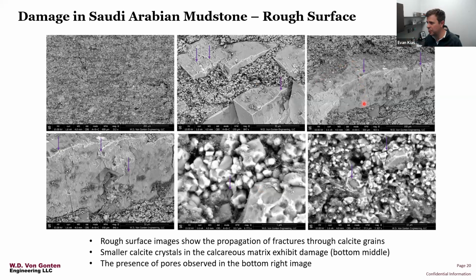You can see nice examples here of tortuous fractures created by shear stress, some spalling at the grain surfaces, and individual grain crushing. So we do see a lot of damage in the sample.